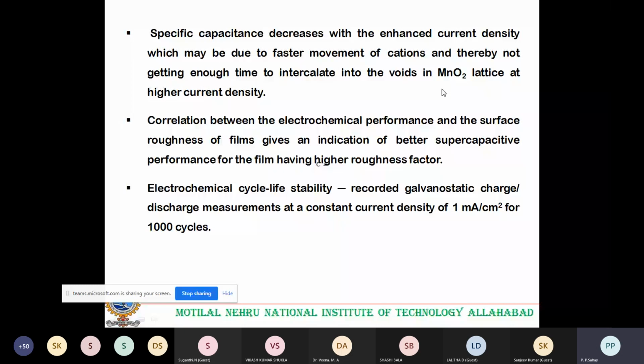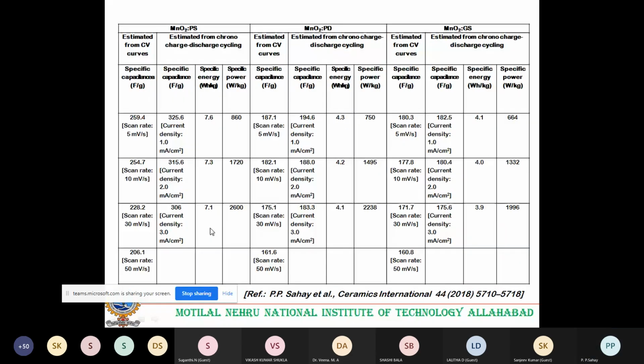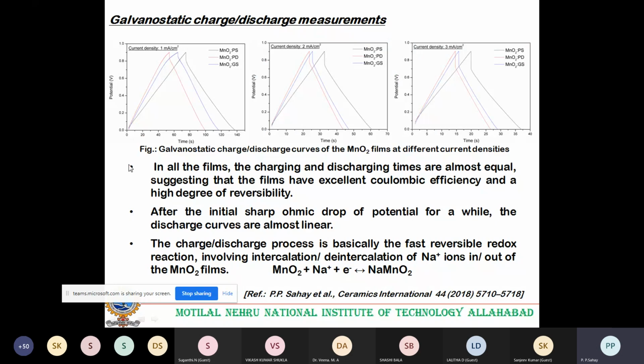Correlation between the electrochemical performance and the surface roughness of the film gives an indication of better supercapacitor performance for the film having higher roughness factor. That is, if the surface area of the film is more, that will favor better supercapacitor performance. And we have also carried out electrochemical cycle life stability. To study that, we recorded the galvanostatic charge discharge measurement at a current density for 1000 cycles. This graph repeated. This is one cycle. So this way we carried out 1000 times.